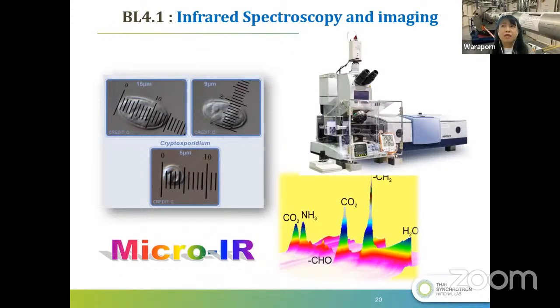The next beamline is beamline 4.1 in infrared spectroscopy and imaging. This one is a combined technique with the infrared spectrometer and the microscope. So you can get information on the size of the sample using the microscope, and you can select which area you want to get the chemical mapping of the sample, because this can measure the organic substance in the sample.